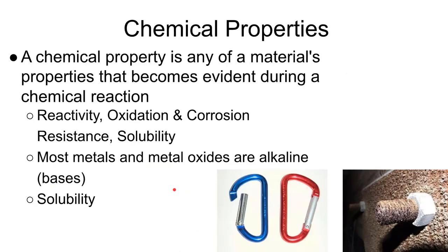We should draw a distinction between oxidation and corrosion because they are not always the same thing. People often say rust equals oxidation, but oxidation can also be beneficial. The colorful anodized parts shown here have oxidation grown artificially through a process called anodizing. When you anodize aluminum, it grows a porous layer of aluminum oxide; you can fill that porous structure with a dye and seal it with boiling water, resulting in a nice, permanent, very hard aluminum oxide coating on your parts.